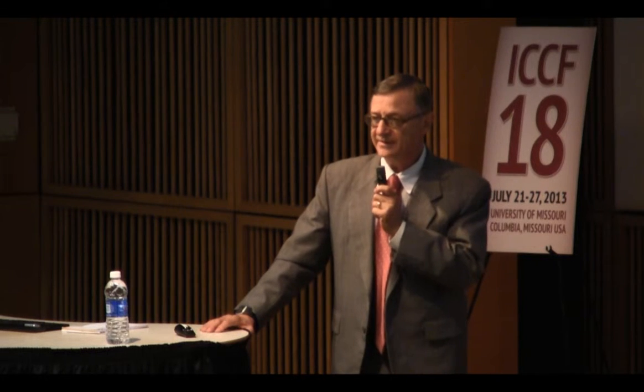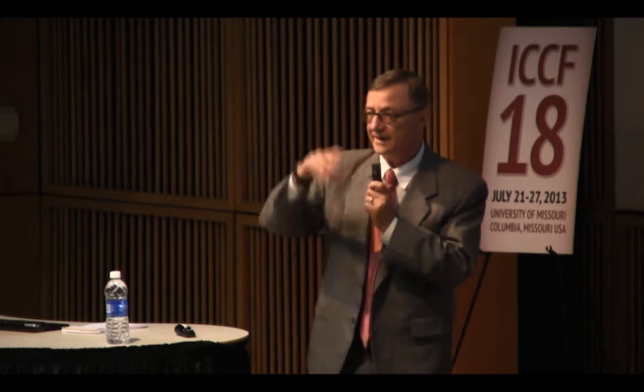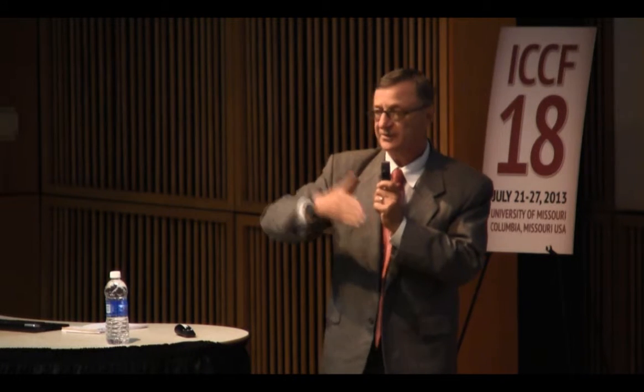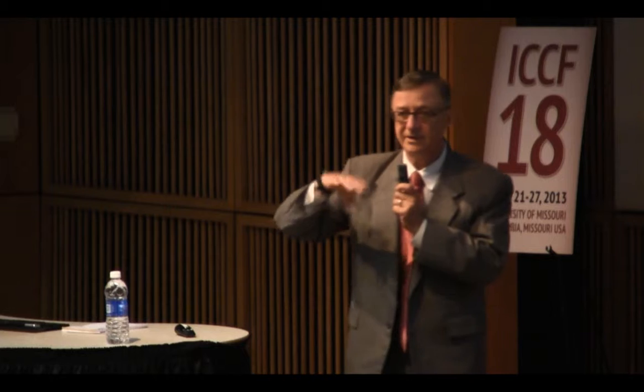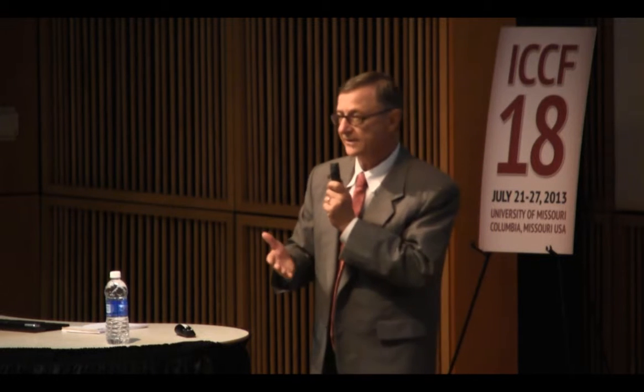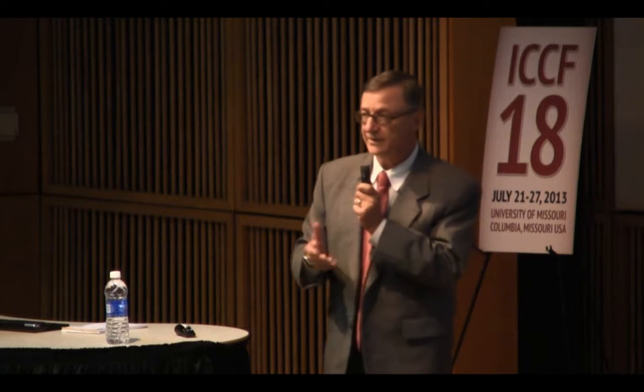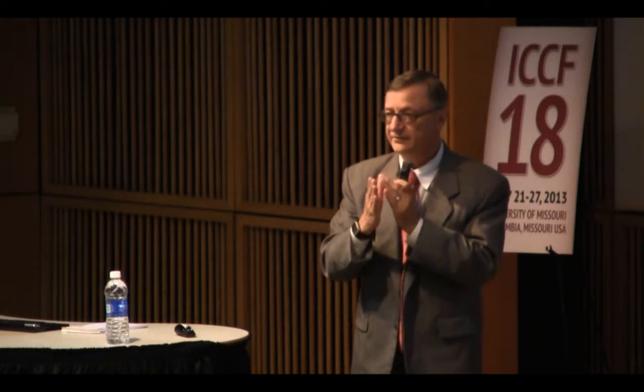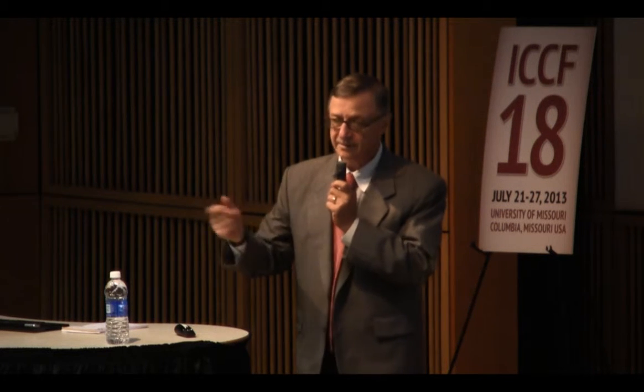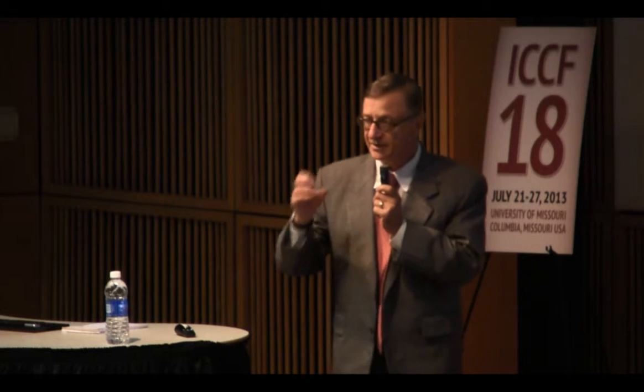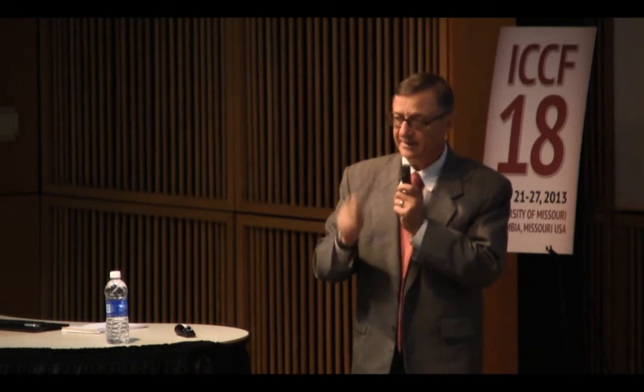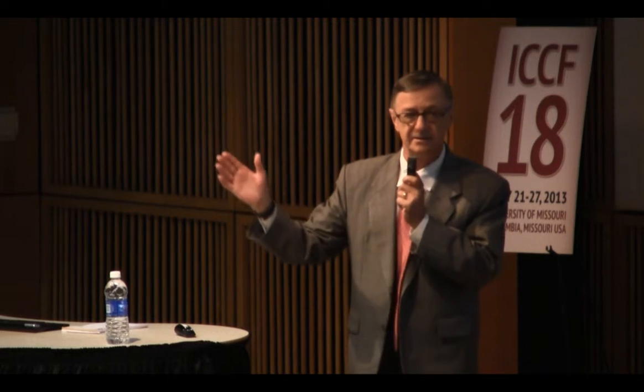But if you ion bombard silicon, amorphize it, at the interface between the amorphous material and the crystalline material, you have a lot of damaged but still crystalline material. It's normally thought that when you anneal that damage out of silicon, you have to go to, say, 600 degrees. But we found that at 250 or 300 degrees, that region in the interface annealed out very rapidly. It was later realized that that was a limitation in the lateral resolution of an ion-implanted dopant, because that damage annealed out quickly, and those defects in their annihilation transported the dopant laterally a long way. Okay.